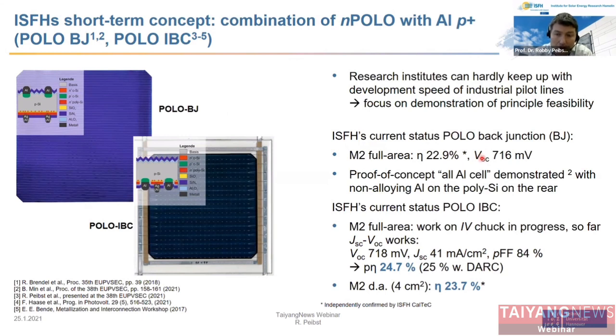And recently we have also shown a proof of concept all-aluminum cell, which does not only contact the front side with the aluminum grid, but also contacts the polysilicon on the rear with aluminum, which is a very attractive version cost-wise. For the IBC version, we found out that it's not only challenging to develop the cell itself, but also to develop an appropriate measurement technology.